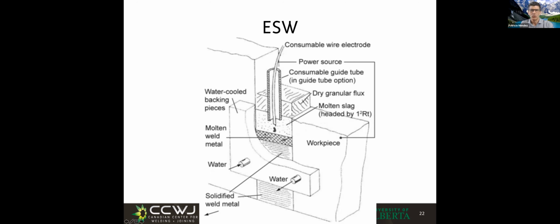Now, what people do is put these backing pieces. Typically, these are water-cooled shoes, left and right. So they're blocking this line of view through the plate. And these shoes, together with the joint prep, make a kind of square joint prep, right? And then I start melting the electrode and I move up the shoes.